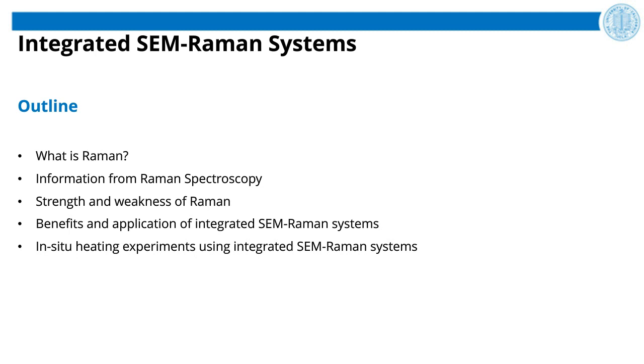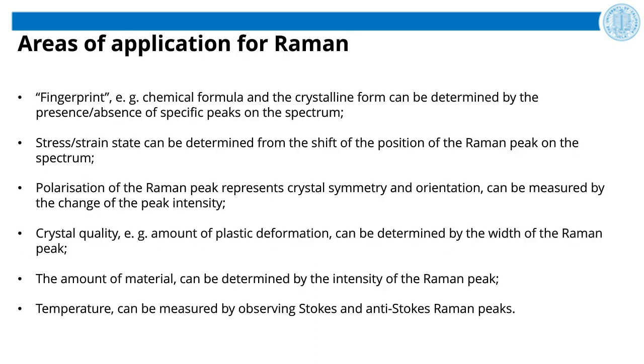Well, the Raman effect was discovered back in 1928 by Professor C. Raman, and it is a light-based technique. When monochromatic light shines into a material, we can get elastic Rayleigh and inelastic Raman scattering of light. Some photons set lattice modes vibrating, some photons change their energy. Energy change depends on the masses of the vibrating atoms, the nature of the chemical bond, and physical effects on chemical bonding such as stress and crystallinity, and the intensity of scattering depends on the number of molecules present. In other words, this technique is quantitative.